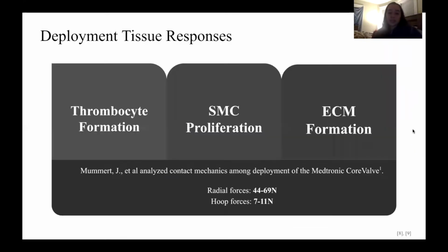We also looked at the interaction between the stent and the surrounding aortic tissue during deployment of the valve. During insertion, the crimped valve is expanded by radial forces through the balloon expandable mechanism. One study analyzed the mechanical properties of the Medtronic CoreValve and found these radial forces to be between 44 and 69 newtons, which translates to hoop forces of about 7 to 11 newtons.